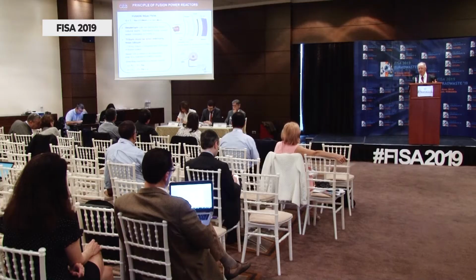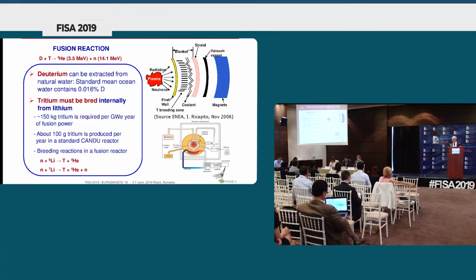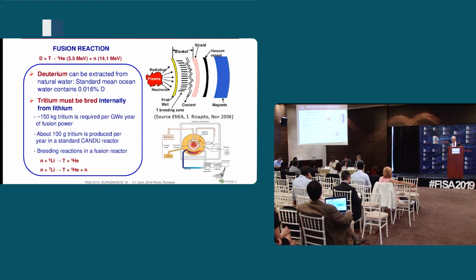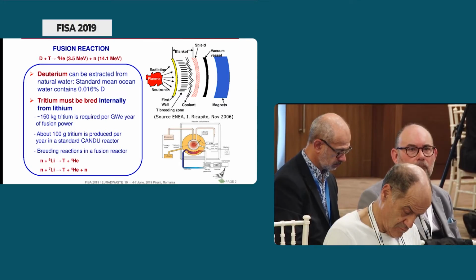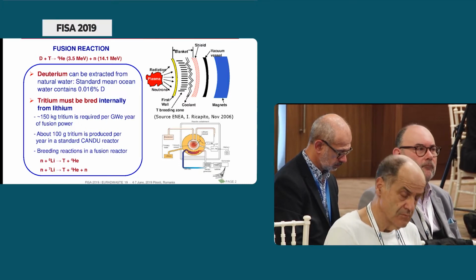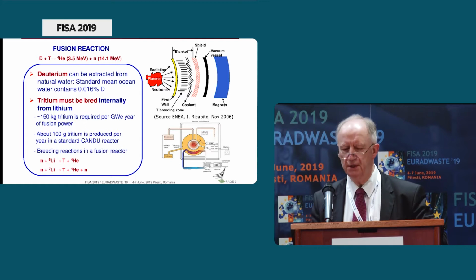There are two missions that are crucial for this first generation of fusion, deuterium-tritium. First of all, to recover the energy that is carried by the neutron. This is 80% of the fusion reaction. The neutron slows down in the blanket itself, and you have to recover this energy at a sufficiently high temperature to drive a conversion cycle with sufficient efficiency, meaning the blanket should operate above 300, say 400, maybe 500 degrees Celsius.